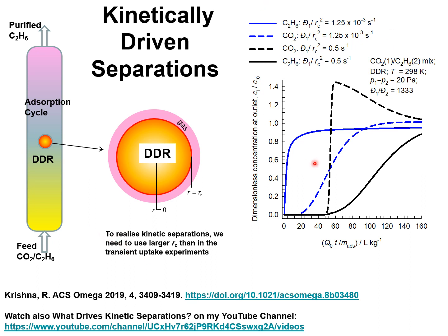So the message here is that for kinetically driven separations, we need to use crystallite sizes that are large enough to lead to significant diffusional influences. And in this set of calculations, the time constants need to be lower in value than, say, those used in the uptake experiments.